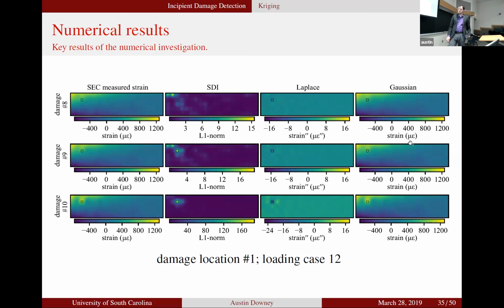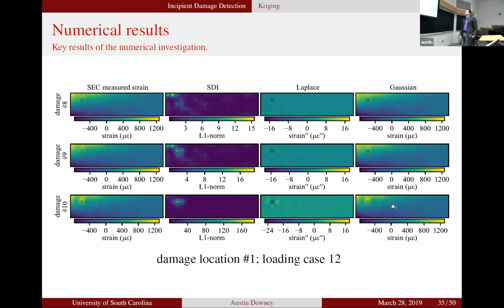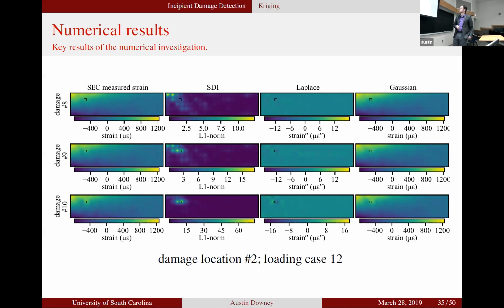And then in damage case 10, you might be able to see some damage there. It's a little debatable. I definitely wouldn't stake anything on it. But the SDI algorithm clearly picks up the damage, and Laplace doesn't pick it up. It picks up damage around it, but the Gaussian starts to pick up some damage in that location. So the SDI is able to pick up damage before these other 2 algorithms.